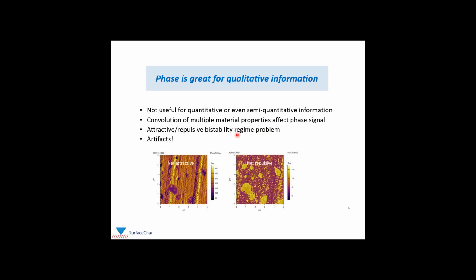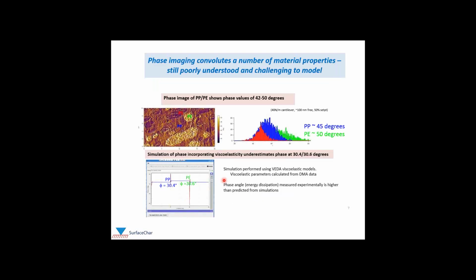Another common problem for anyone who's practiced phase is an artifact and bistability problem. So we can have a lot of artifacts in phase due to the bistability of imaging in the attractive or repulsive regime. And here's an example of a sample that I imaged, identical area in the net attractive and the net repulsive regime. And clearly there's a contrast reversal issue. And the images are really showing and highlighting different features. So in terms of trying to interpret the phase as a mechanical property, it doesn't do very well. Like I mentioned, phase imaging convolutes a number of material properties. And so quite frankly, it's still poorly understood and very challenging to model.